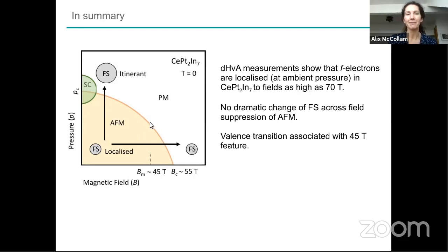It's very difficult to do high pressure measurements at field, but of course people can do them. In recent years there's been development of plastic pressure cells that allow you to get up to very high pressures. There have been measurements of cerium rhodium indium-5 in this region of its phase diagram recently, and features such as nematicity that weren't expected are seen up there. But for this material, the data that we have are all at ambient pressure at high field, and the highest data under pressure is up to about 18 Tesla or so. Thank you.